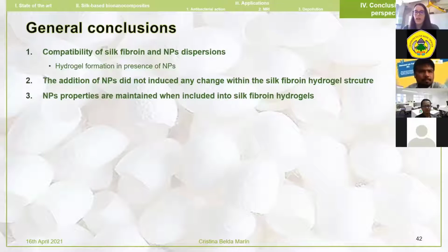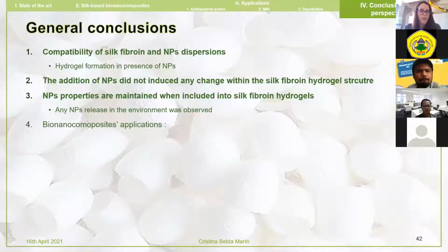We have not seen a change in this hydrogel structure when nanoparticles were incorporated. Moreover, the properties of such nanoparticles are maintained when they are in silk hydrogels, and we have not seen nanoparticle release in the environment, which is very important concerning nanoparticles today. Finally, I have shown the application of bionanocomposites for silk with silver. We have seen an antibacterial action by contact rather than by release.